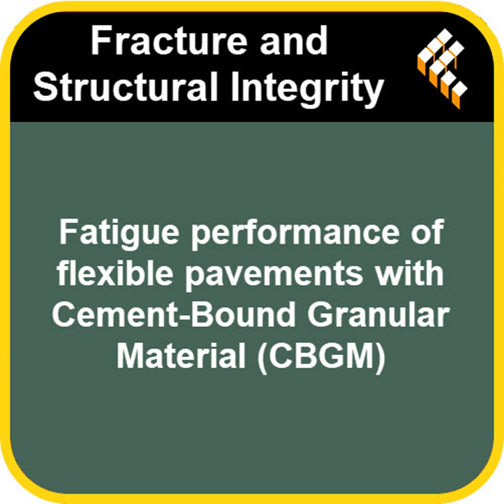Yes. And for the 4th configuration, type 4, which was a bit more robust, Dempsey predicted only 48 load repetitions, still practically immediate failure. But De Beer, for that same type 4, estimated an astonishing 2,858,260 repetitions. 2.8 million repetitions versus 48. Correct. In that type 4 case, the calculated tensile stress was 0.40 MPa, which is below Dempsey's 0.48 MPa limit, only just, leading to the 48 reps calculation. But the calculated tensile strain was 85.06 microstrain, well below De Beer's 125 microstrain limit, hence the millions of reps prediction.